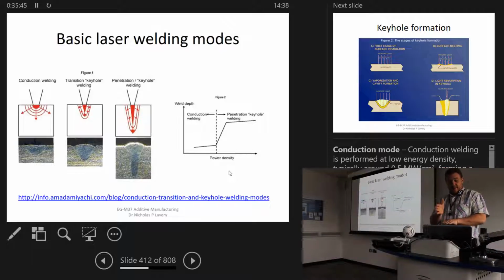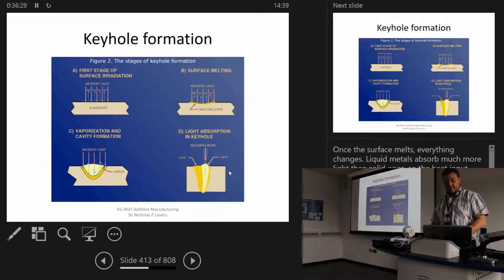So when you first get your laser, you switch it on, you get a nice continuous kind of semi-elliptical shape of melt pool that comes down. As your power goes up, and more specifically, we're looking at the power density, as this goes up, you get a transition between what we call the conductive mode of melting, and then it transitions through to a keyhole mode. And that shape that you get there, you can see quite clearly, it's like a shark's tooth, and it starts to penetrate more into the substrate. That is called transition from conductive welding through to keyhole welding.